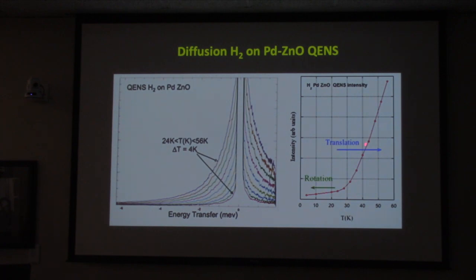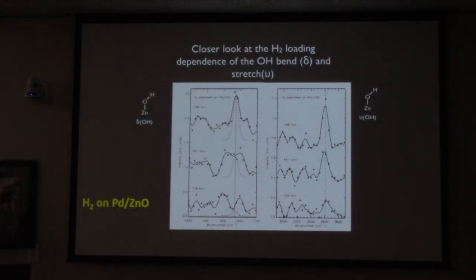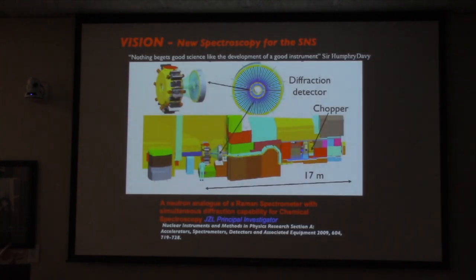And this is, if you can follow that plot, and you notice that right around 35 to 37 Kelvin, they actually start to translate. And they're complicated calculations. The interesting thing is what happens on the surface. We've measured the fact that the hydrogen actually interacts with the zinc oxide palladium decorated surface. And here are two of the inelastic neutron scattering spectra, one for the OH wag and the other one for the OH stretch. And years ago, you'd never be able to do this with neutrons. That's the bottom line. How did we do it?